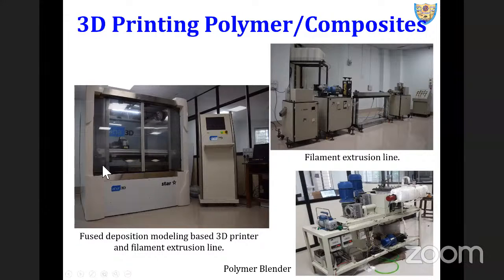Now, we manufacture our own filament as part of this DST project, which got completed in 2020. For that, we have a single screw extruder, which is non-vented type. Here we feed the pellets, composite pellets, into the hopper and draw the wire required for a 3D printer. Generally, two diameters are preferred. One is 1.75 plus minus 50 micron. Second is 2.85 plus minus 50 micron. So that we can manufacture here.